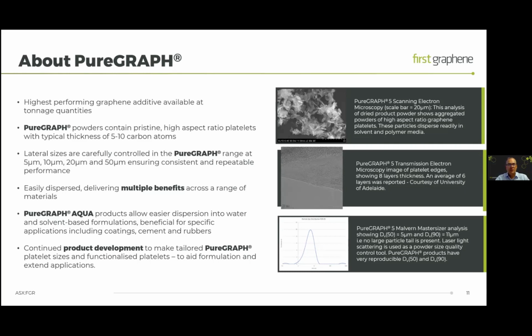Recent work that has just been published by the University of Adelaide, which is a central image on this slide, shows that by doing edge analysis, they calculated that the average platelet thickness in our Puregraph 5 was 6 carbon layers.